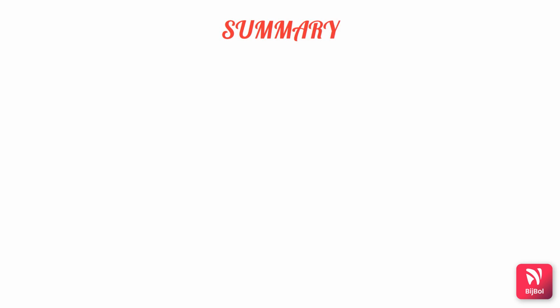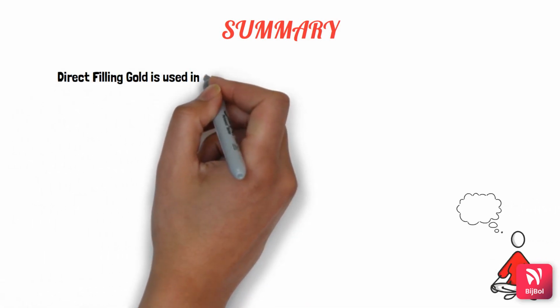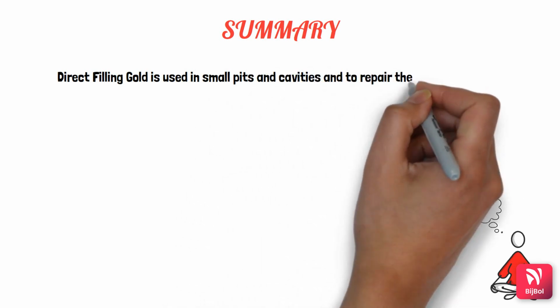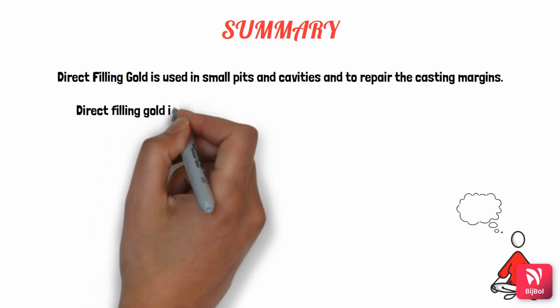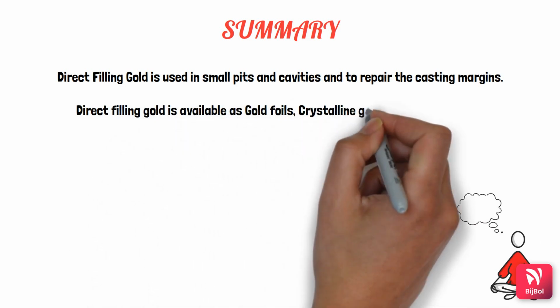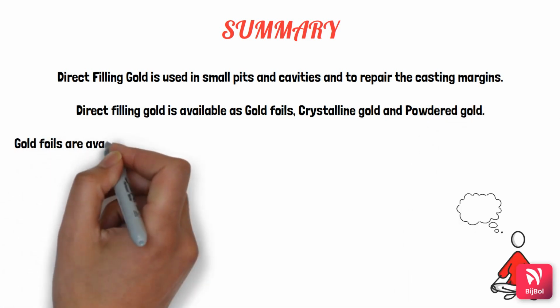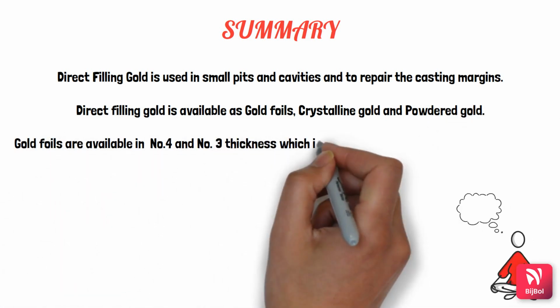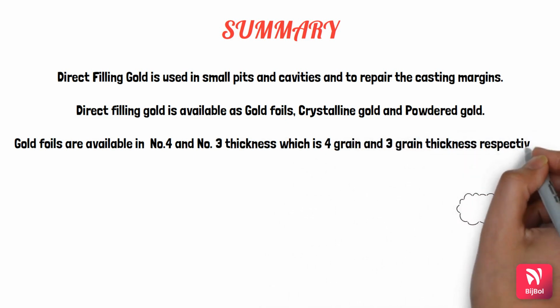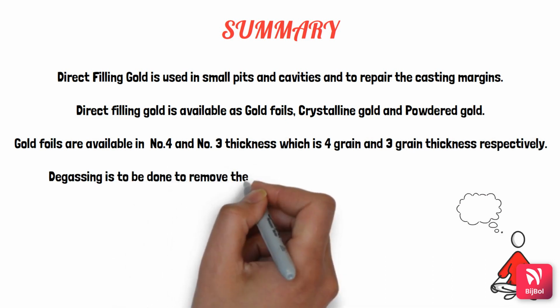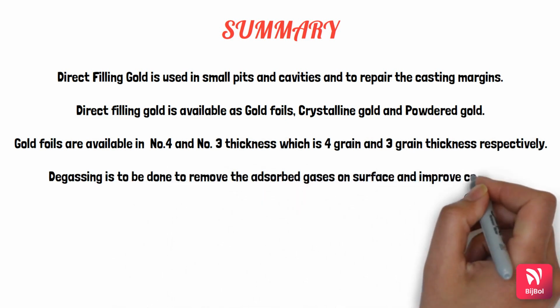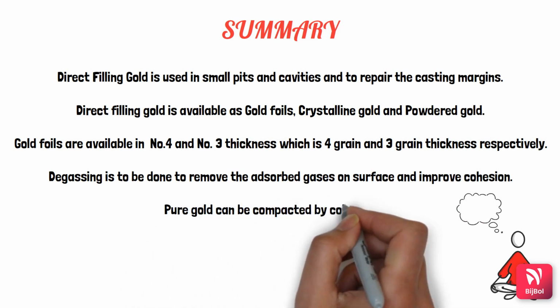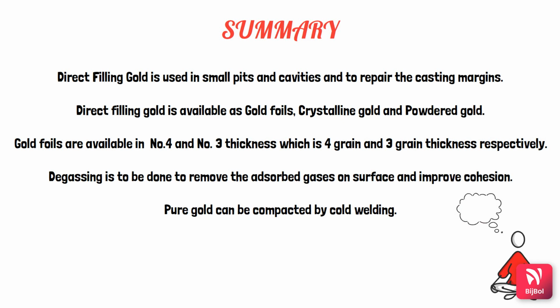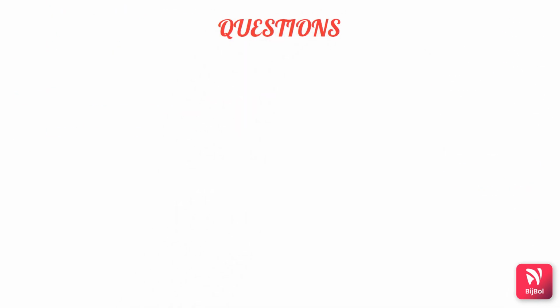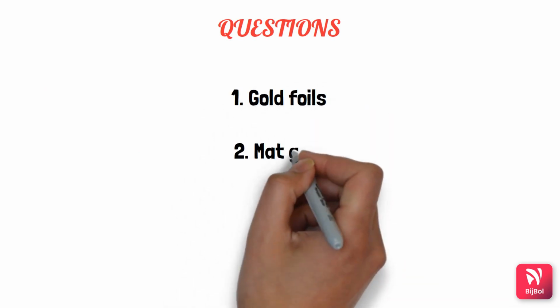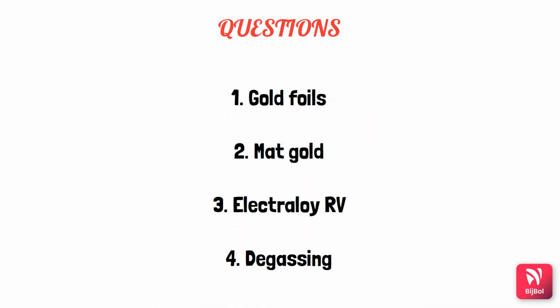Let's have a recap. Direct filling gold is used in small pits and cavities and to repair the casting margins. Direct filling gold is available as gold foils, crystalline gold and powdered gold. Gold foils are available in number 4 and number 3 thickness, which is 4 grain and 3 grain thickness respectively. Degassing is to be done to remove the adsorbed gases on the surface and improve cohesion. Pure gold can be compacted by cold welding. A few important questions from this chapter are: gold foils, Mat gold, Electraloy RV and degassing.